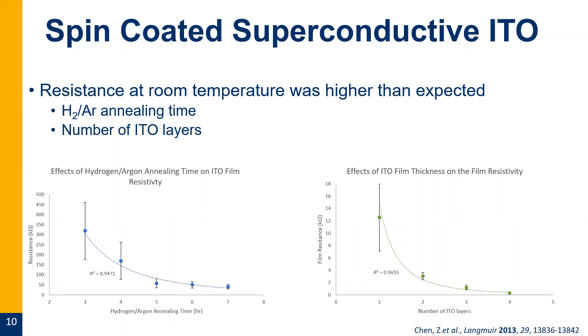We then looked at how ITO film thickness affects resistivity and found a similar trend: as we increase thickness — going from one to four layers — resistance decreases and becomes more consistent between samples. Next steps are characterizing films via AFM and electron microscopy techniques, as well as ellipsometry to characterize their optical characteristics, making sure they're transparent where needed and that they actually superconduct.